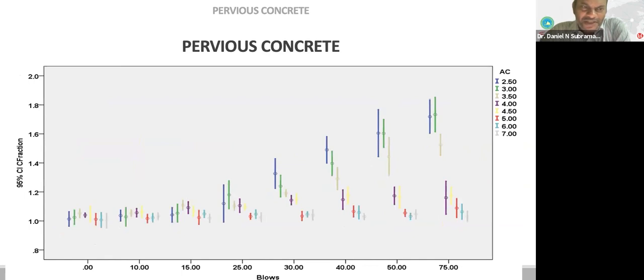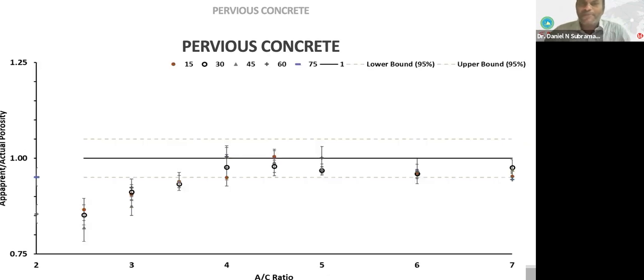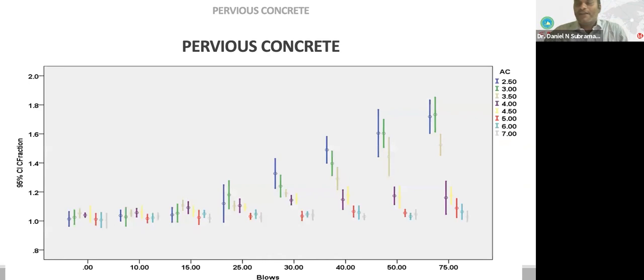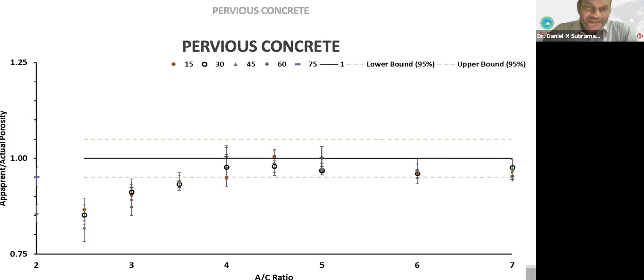So this is showing us the fraction of actual porosity and computed porosity. That's the fraction that we're talking about. Here also you can see that a distinct pattern is there between 3.5 and 4 aggregate to cement ratio. Therefore, we come up with the idea that the optimum is happening somewhere there. So no matter how much you put in less than 4, it is not going to help you with pervious concrete. So this is again showing the apparent, the measured porosity and actual porosity.